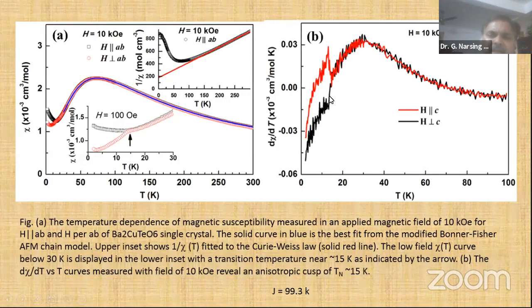Okay, but at low temperature, around 15, there is an anomaly in dχ by dT. Here also there is an anomaly. So once we saw this type of anomaly, we measured at low magnetic field. There are two different directions the curve is going at 15K. Perpendicular to AB it's going down, and parallel to AB it's going up. That means the spins are acting in a different way in that crystal. So at 15K there may be a possibility of long range ordering, but only in one direction, not all directions.